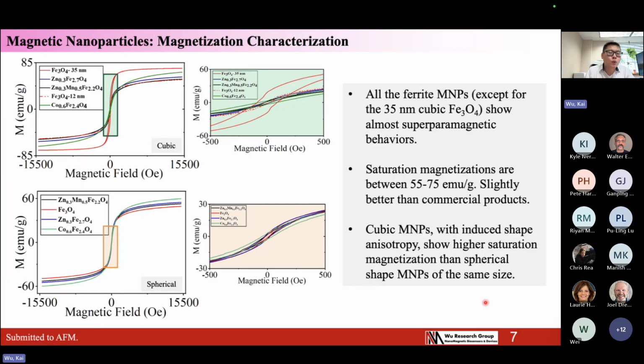Next, we measure the magnetization curve of these particles. We also compare with the 35 nanometer Fe3O4. As you can tell from the slides, the 35 nanometer Fe3O4 is not superparamagnetic. You can see a very large hysteresis loop from this 35 nanometer Fe3O4 with the red curve. For the other particles, the coercivity is almost zero. So we claim that they are superparamagnetic and they can be used for biomedical applications.